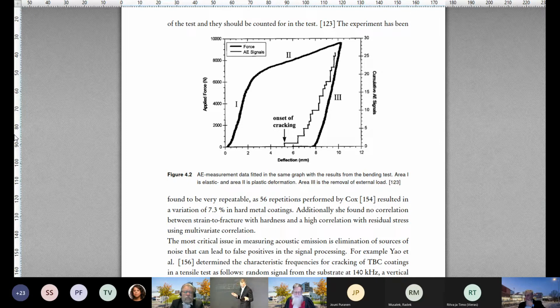And finally, what you see after Roman numeral 2, before 3, at the end point, is that you have actually pulled the substrate and the coating apart, so there are some open cracks. And there's plastic deformation of the metal substrate. When you let go, the substrate doesn't go all the way back; it stays a bit higher by the amount of plastic deformation, which would be the deflection of 8 millimeters. I guess it's measured from, I don't know where. But in any case, it would stay here. Some cracks would also stay open because of that.